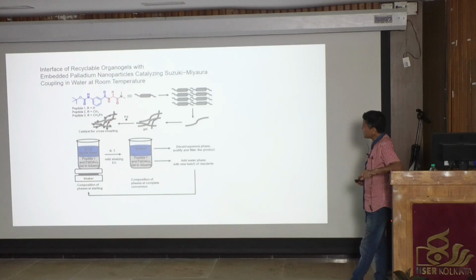For that purpose, we developed this peptide, which again contains meta-aminobenzoic acid. Here we have a natural amino acid, whether it is glycine, alanine, or phenylalanine. And then at the end we have the C-terminus with dimethylamine as the capping. The peptide is supposed to form this helical structure. It will form fibers, and the fibers will form a gel by restricting solvents.